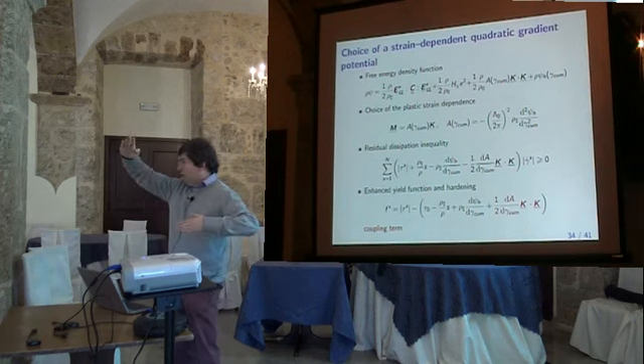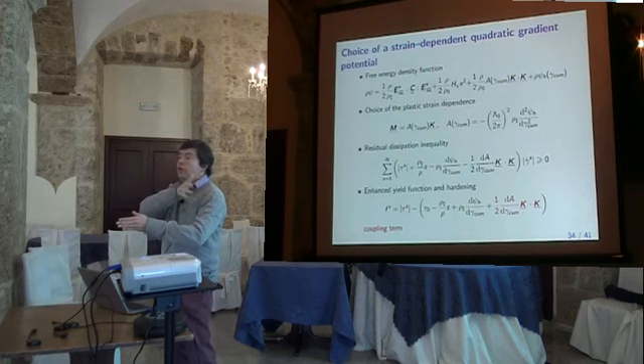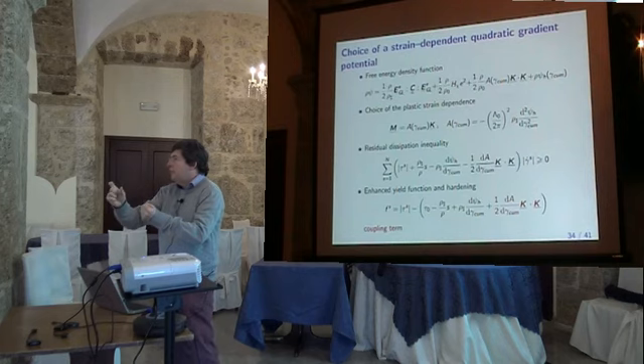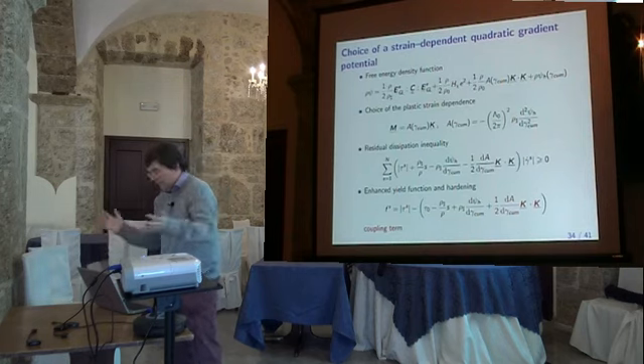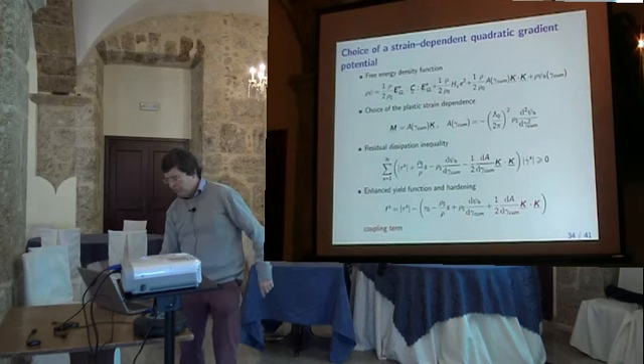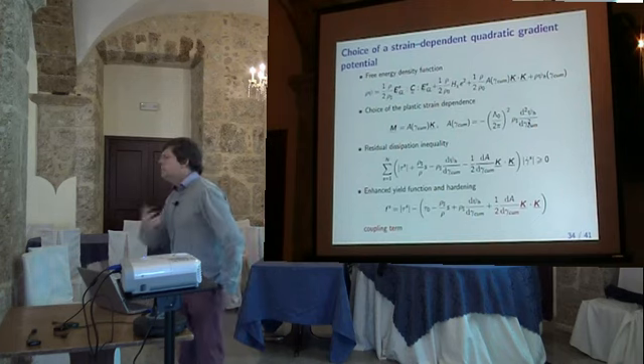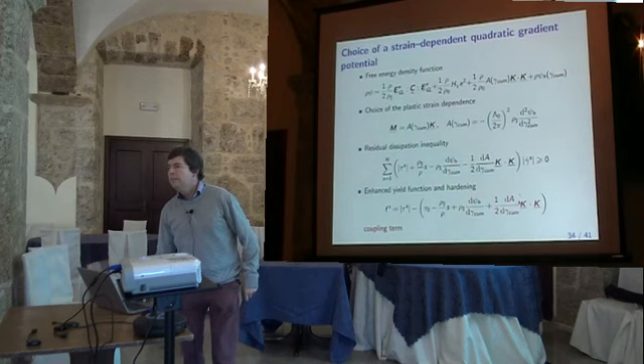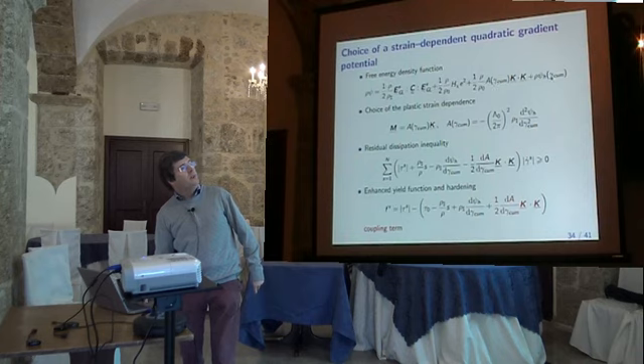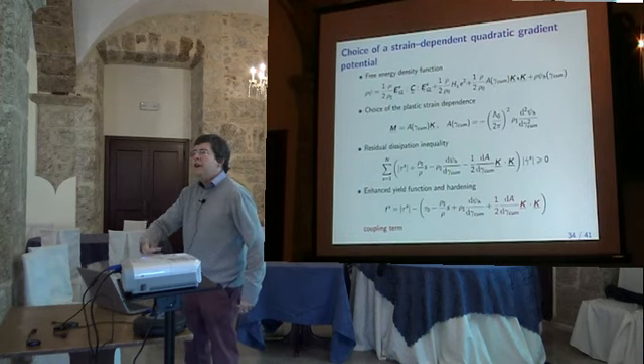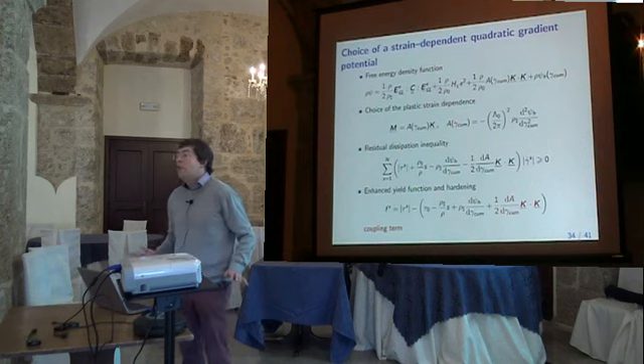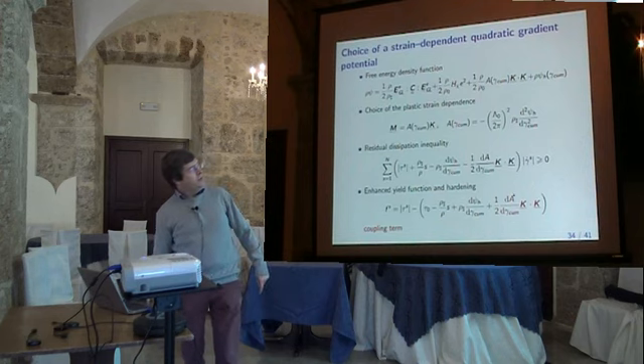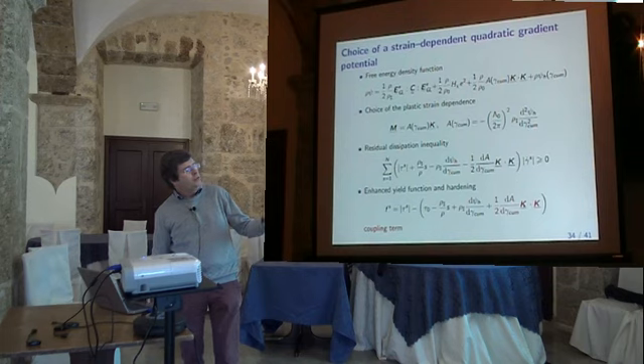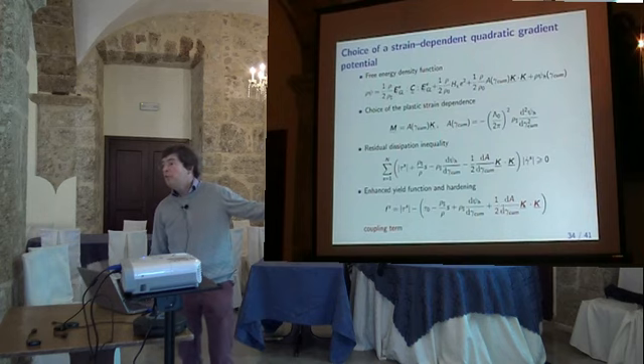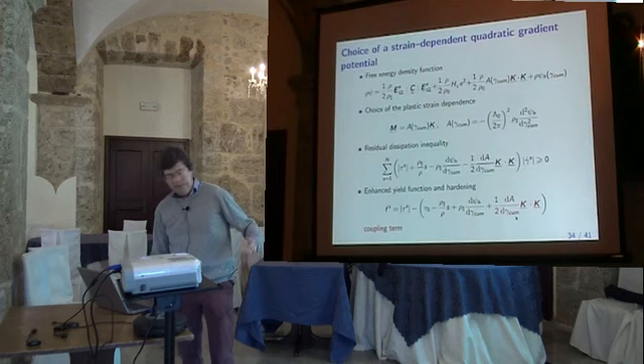Because if you change the tangent modulus, you will change the bandwidth if you take the previous model, which was very simple. So we adapt the length scale, the intrinsic one, so that you have a constant bandwidth. It's not exact, because once you propose this, the thermodynamics comes back and tells you that there will be a coupling. Because, of course, there is a coupling here between this variable and this one. So you will have some additional nonlinear terms which come into play. And so we are not sure it will work, in fact. And so this is this additional hardening. We have a new sort of hardening, which is due to the gradient term, which was not the case in the previous, because A did not depend on gamma cum. So this is a new term.